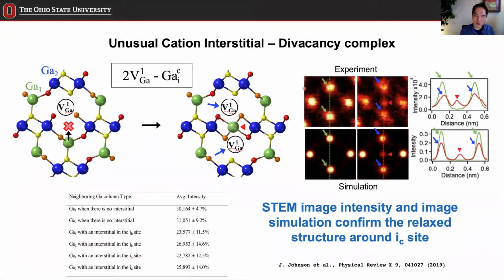Okay, so what we try here is, rather than just looking at the intensity of the image, we quantify the intensity so that we can verify the location of these individual vacancies, in addition to the extra intensity that comes from the interstitial atom. If you look at the experiment here, you have an area where there's no defect, right? So this one does not show any extra intensity. The line profile of that would give you just two peaks: one gallium column, nothing, and the other gallium column. Now, if you draw the same intensity profile across the area where there is extra intensity from the interstitial position, of course, because of this extra interstitial column, you're going to have this extra intensity. But interestingly, the nearby gallium column intensity is always going to be low.